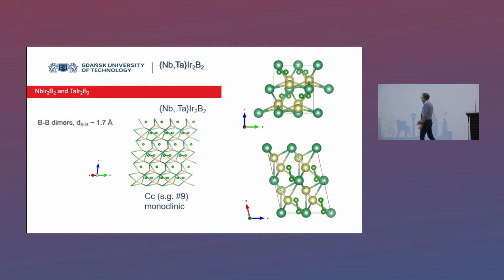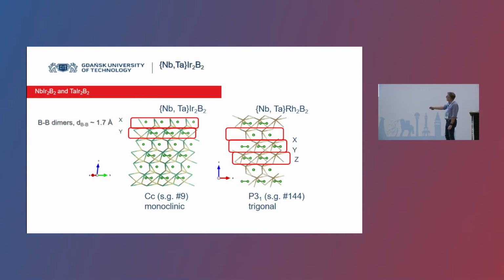How does it work? How does it look? Well, it's complicated. It's very complicated. So I'm not going into details, but the most important point here is that we have the boron-boron dimers. You see that the distance between boron atoms is only 1.7 angstrom. And even more, the boron-boron dimers are aligned in different directions. So this is the system we worked on with iridium. And you can ask me, is there any link between this 1-2-2 system and that 1-2-2 system with rhodium?